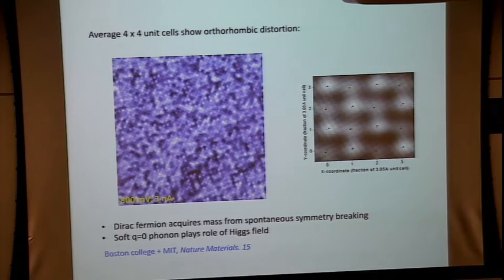So this tells us that structural distortion is really present. And further, there's a bulk X-ray scattering experiment showing that in lead tin selenide at this alloy composition, the bulk is actually still non-distorted. So the distortion only occurs on the surface.